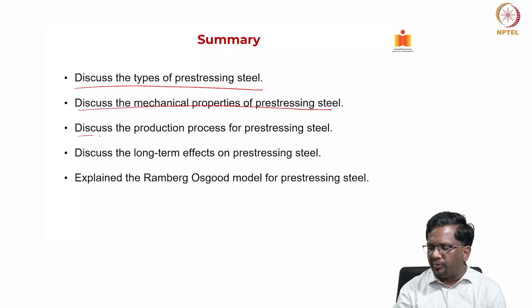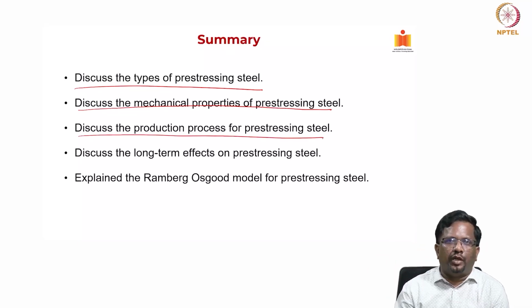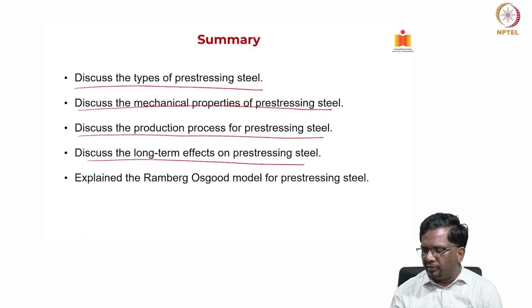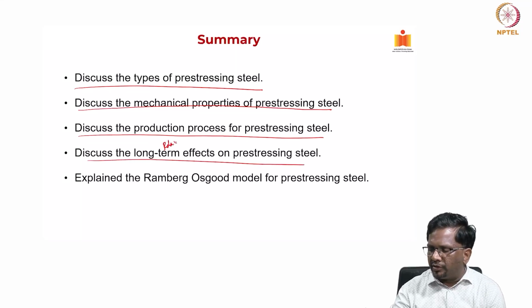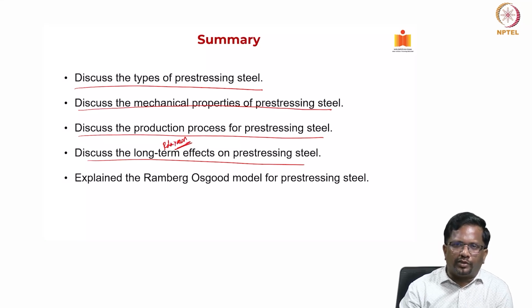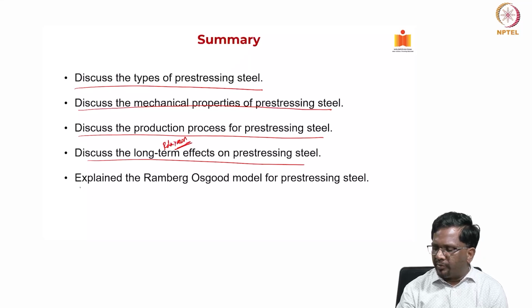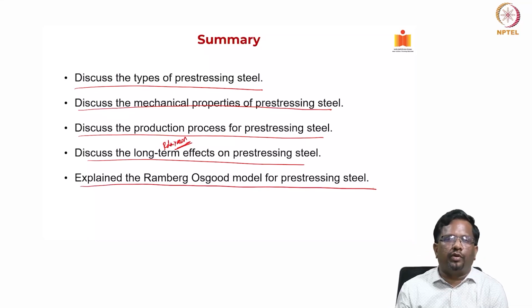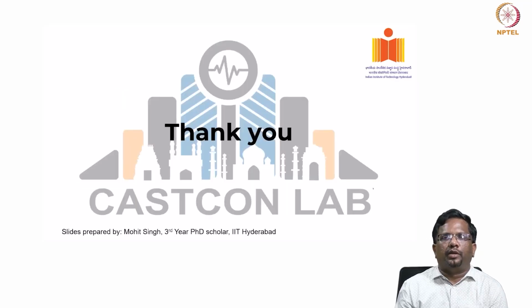And we also discussed the production process of prestressing steel, and we have discussed relaxation loss, okay. If you are using low relaxation strand, which is better, the loss due to relaxation will be less. And we also explained how to use the Ramberg-Osgood model for predicting the entire stress strain curve of prestressing steel, right. So, with that we are completing this first module.